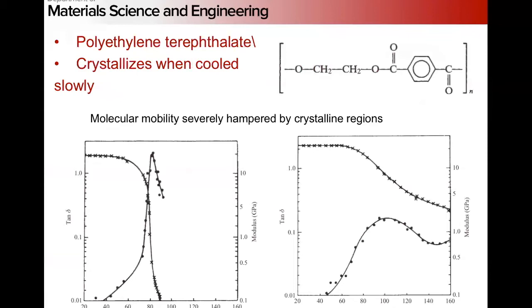Our crystalline interactions are going to be some of the strongest types of chain entanglements that we can have, right? So crystalline regions are going to severely hamper molecular mobility. So we will have a stiffer, higher modulus at a given temperature in a semi-crystalline polymer than in an amorphous one. Notice a couple things though. Our tan delta peak appears at roughly the same temperature, but it's much narrower in the amorphous than in the crystalline. So we have a wider window of viscoelastic behavior in a crystalline polymer versus an amorphous polymer.